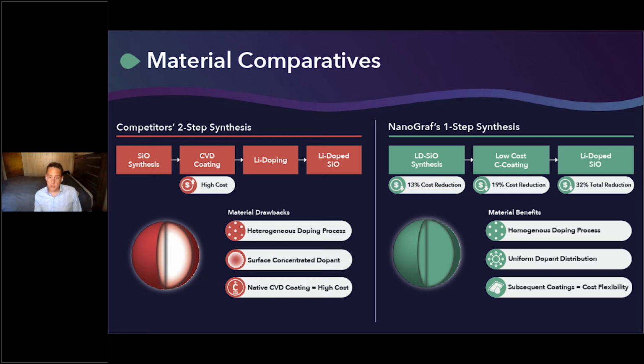And what we've been able to do is basically use a one-step synthesis where the doping process happens while the material is being made. We've developed a low-cost carbon coating, and again, with this process, we're looking at between 30 and 40% reduction in cost. And of course, that's great news for EV makers who are obviously trying to push costs of batteries down, but retain that really great performance.